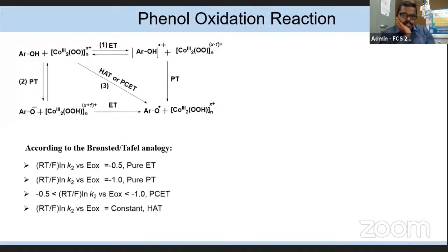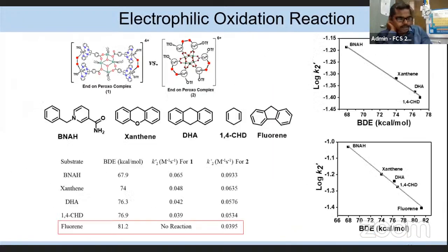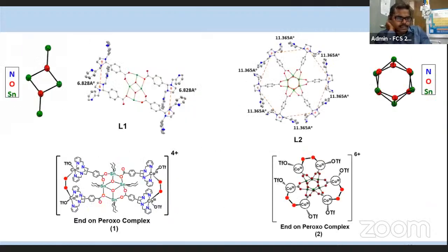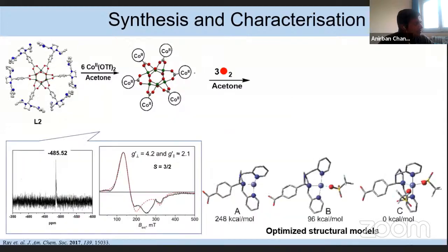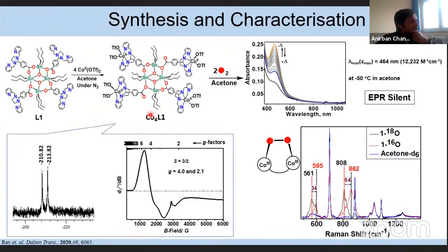Anirban, I have one small question. Why are you getting two tin peaks in the tetranuclear complex, whereas for the hexanuclear you got one single peak in tin NMR? Yes, just one moment. For the tetranuclear system, there are two types of tin center present. These two tin centers are connected with two oxygen atoms, whereas these two tin centers are connected with one oxygen atom. So there is not a huge chemical shift, but the signal is just split.